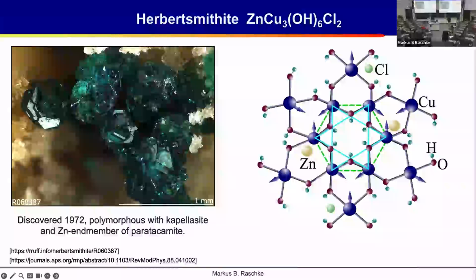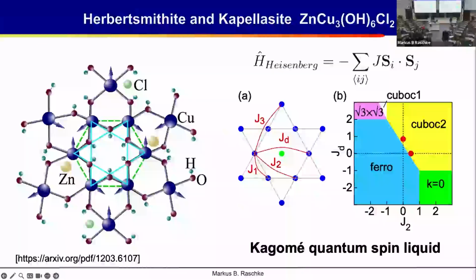There's another interesting side aspect to this. There are different types of these minerals discovered in South America, in these copper deposits in Chile and the Atacama Desert. And there are derivatives of these minerals which are named after Atacama, so Atacamite. And so here's this Kagome lattice pattern again. Here are the copper cations. And in this material, because the copper has a weaker spin, it's only spin 1/2, the spin orientation stays completely in this lattice plane. And surprisingly, they indeed discovered this spin liquid behavior in this material.